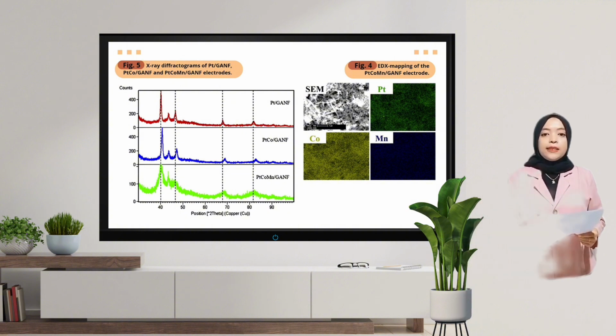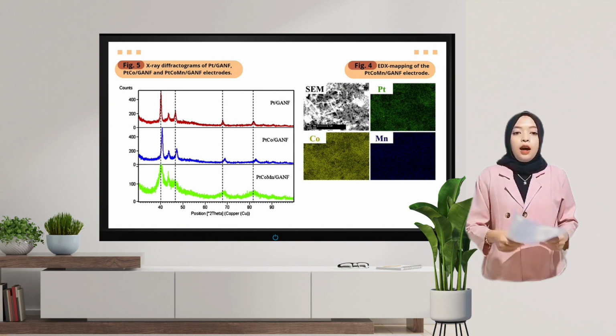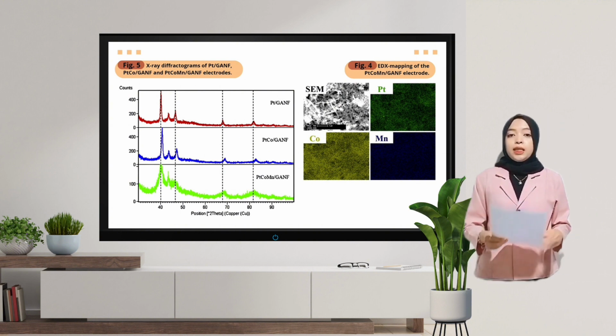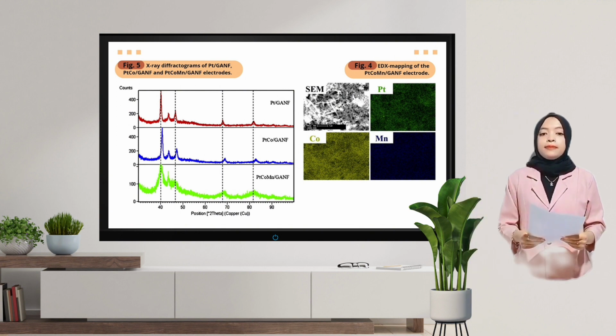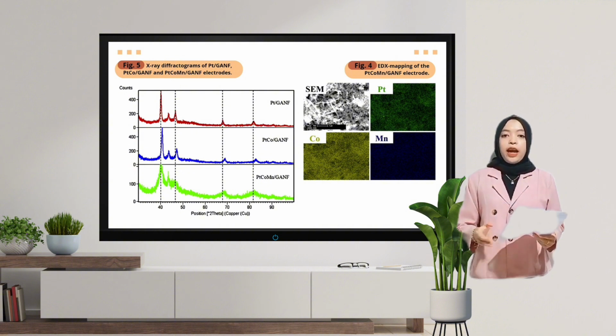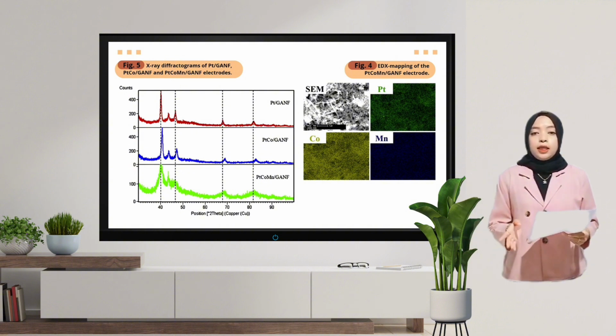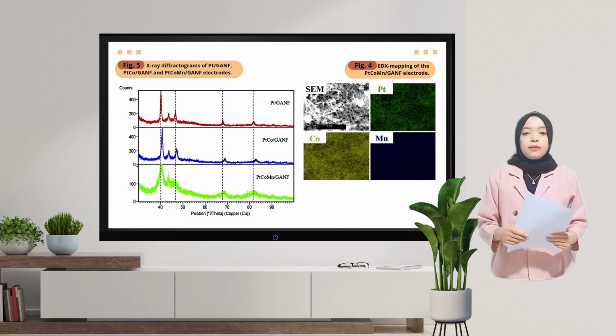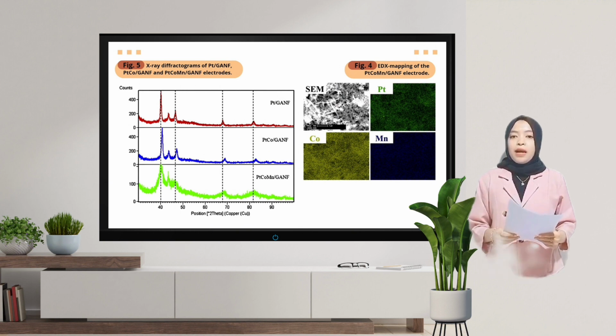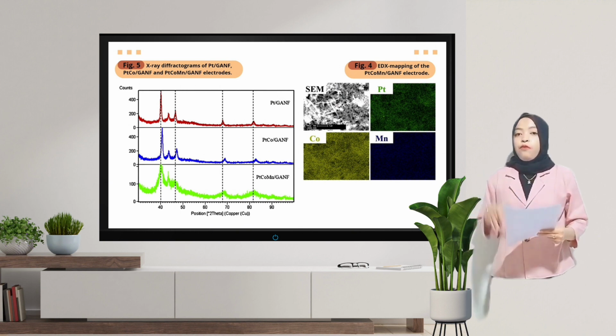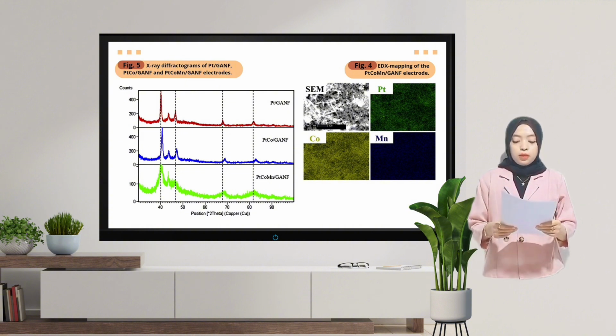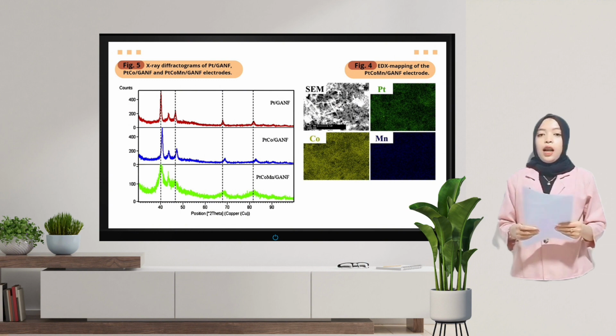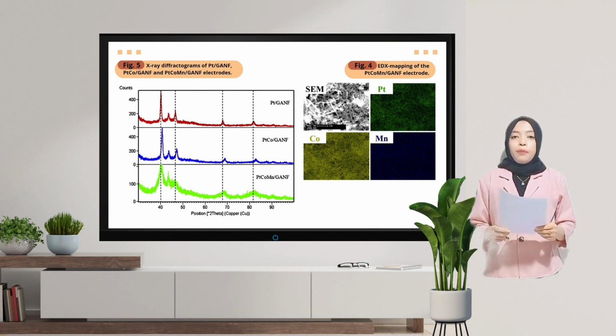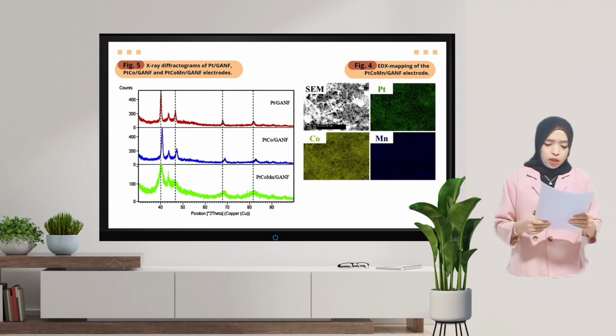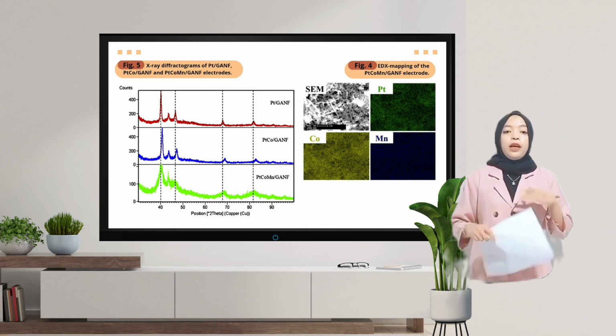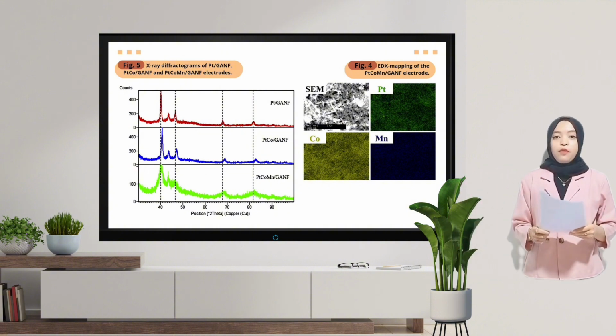Additionally, an EDX mapping, Figure 4, of a selected region of the platinum cobalt manganese GANF electrode is presented. The distribution of each element is uniform, indicating an increasing degree of alloying between the elements. The X-ray diffraction pattern of the platinum cobalt manganese catalyst, Figure 5, revealed the crystal structure and alloy properties of the particles, displaying the main characteristic peaks of the platinum FCC structure, and no additional diffraction peaks for cobalt and manganese could be observed.